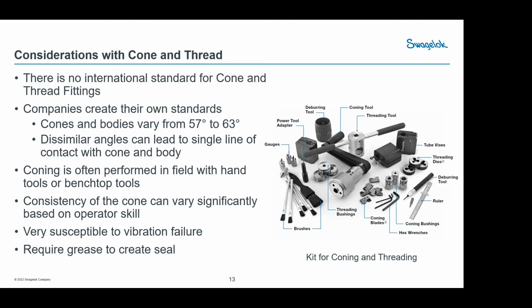It has the cone and threads. It seems to be having a phenomenon where they burp, where they relieve a small amount of gas for a short period of time and then reseal themselves. It makes sense with the way the product is put together, and it may also make sense because one of the characteristics of putting together the seal is there's often grease used on the nose of the fitting.